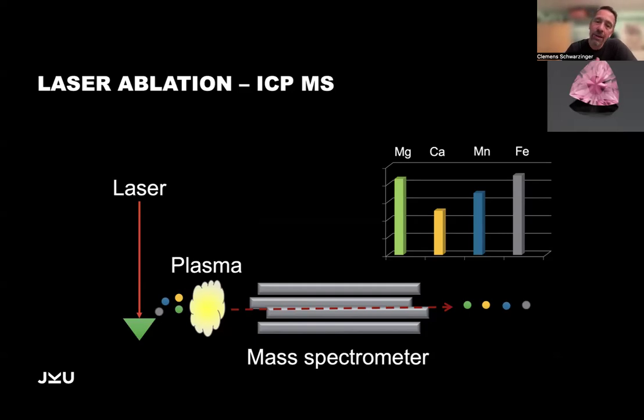This is very often really a pity because the customer says, yeah, please do not destroy my gemstones. But the holes that we're shooting are very small, like 50 microns in diameter and 1-2 microns in depth. And we shoot at 3 positions along the girdle. So if you look from the top on the gemstone, you don't see it. With a microscope, you do see the craters, but if you polish it out, it's not even the second decimal of weight that you would touch.